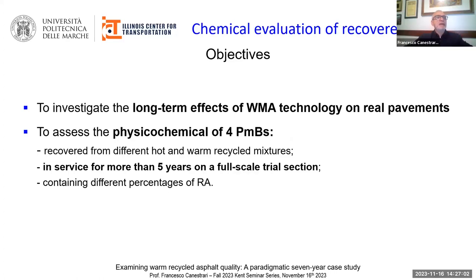Besides the mechanical characterization, we adopted also another approach to evaluate the long-term effects of warm mix asphalt technology on real pavement. This approach was based on the chemical evaluation of different properties of polymer modified bitumens recovered from different hot and warm recycled mixtures in service for more than 5 years, taken from the case study trial section. The binder was recovered from open-graded and dense-graded mixtures containing different percentages of reclaimed asphalt pavement.